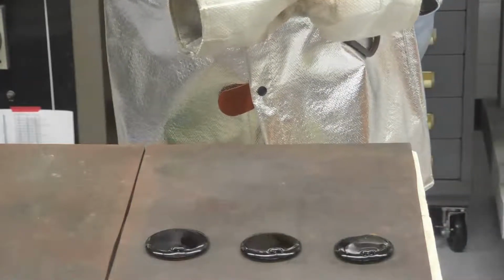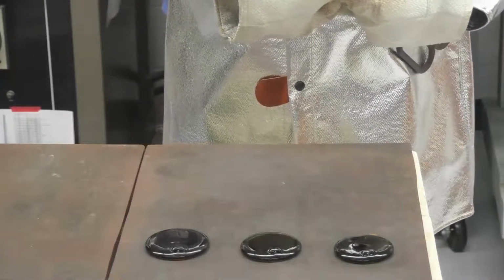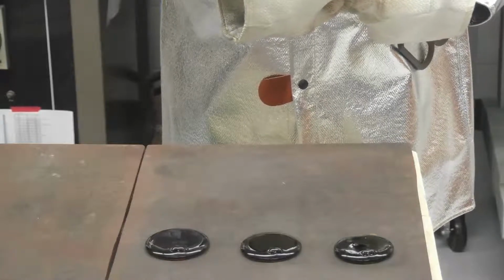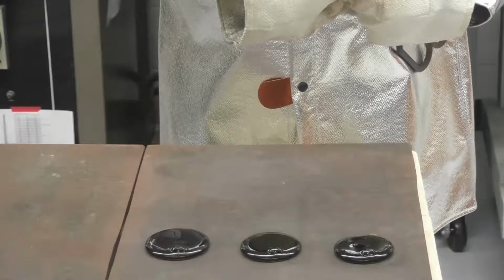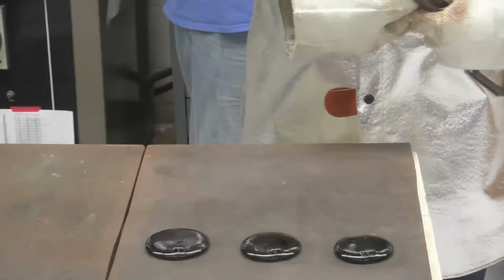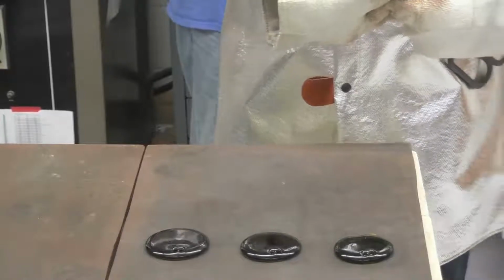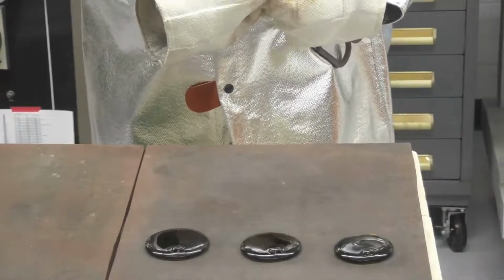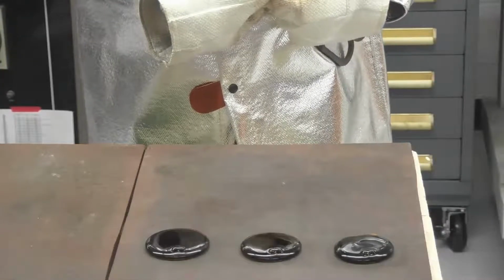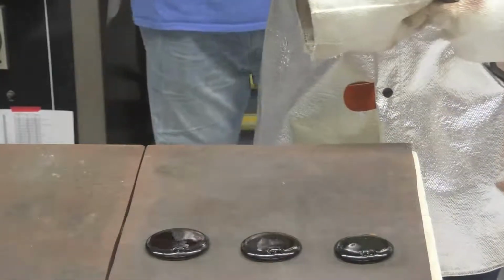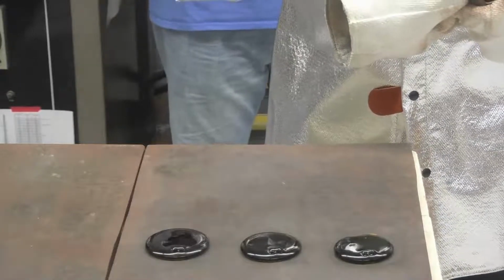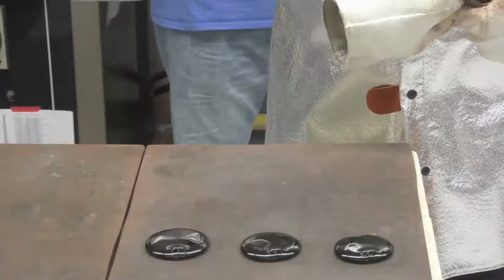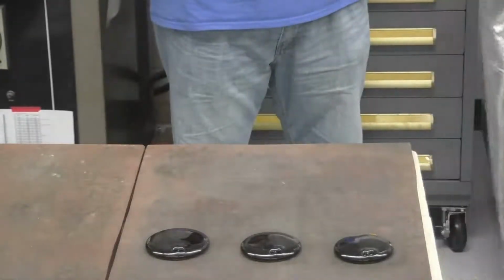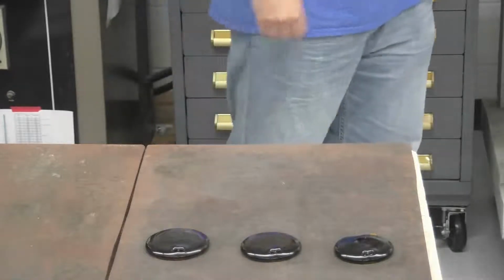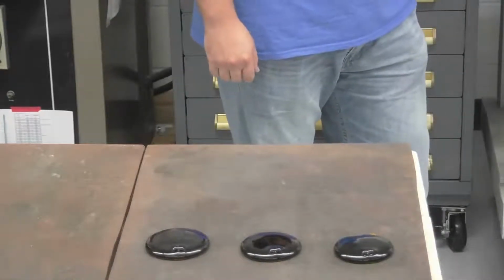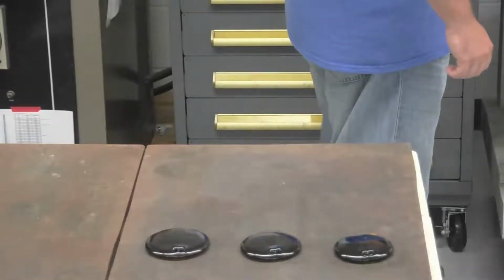The ceramic shrinks at a different rate than the glass. So you probably heard of coefficient of thermal expansion. Because those are welded together, that tension that's formed results in breakage of the glass. This is a process called crazing. And every time you hear that little tink sound, if you watch the glass, you'll see a new crack forming. Like right here, watch those crazes form on that glass. And so it's differential shrinkage. And eventually that'll be just a constant chorus with all these crucibles breaking glass. But since it's stuck, it doesn't actually shatter, it just makes a crack. Great. I'm holding the heat, right? Okay.